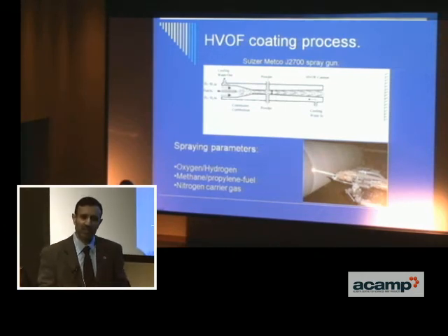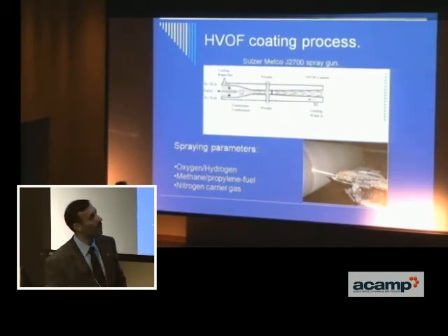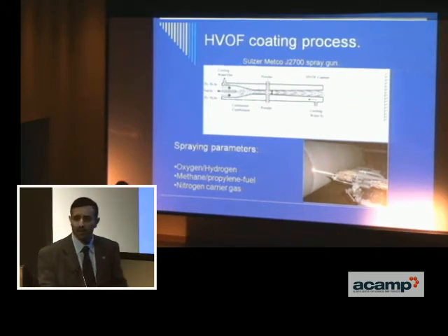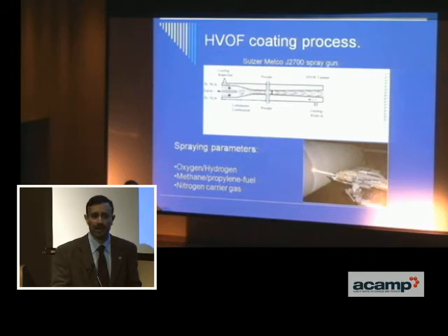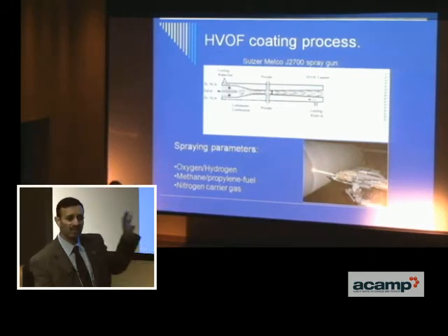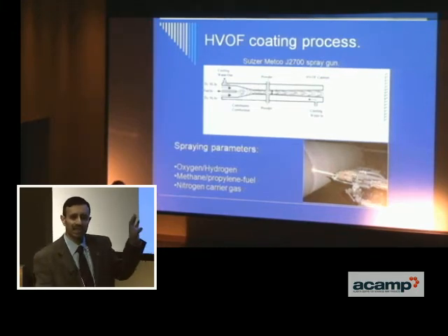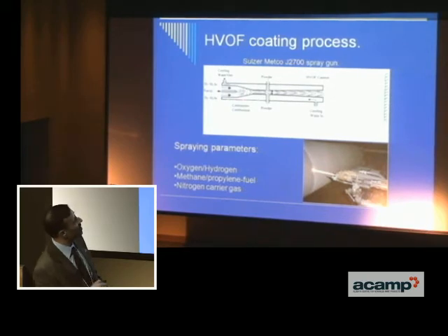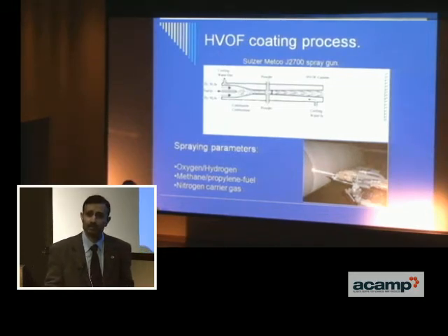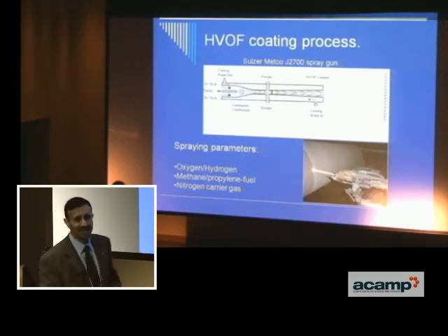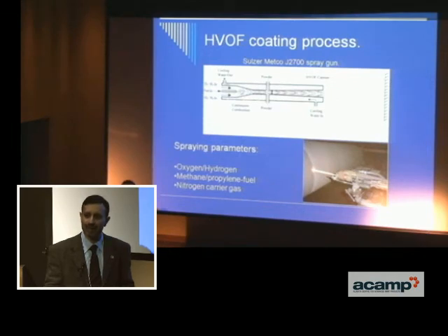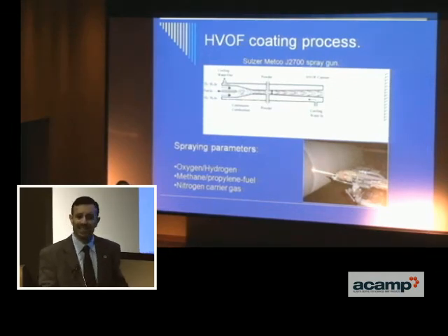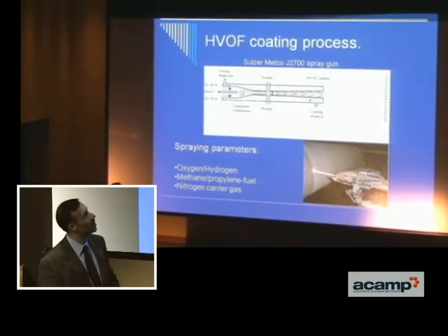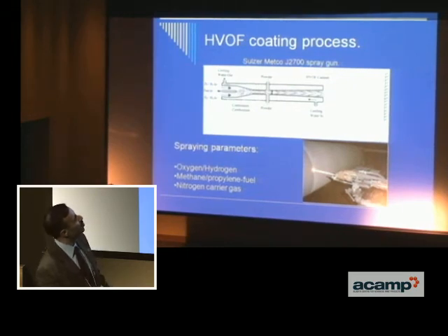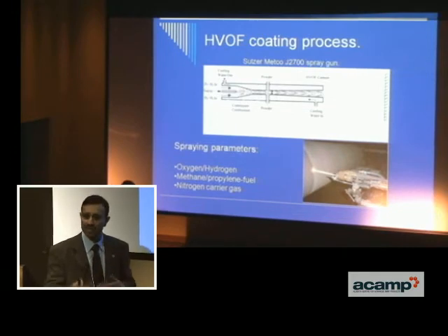So after a lot of extensive comparisons of different types of coating methods that we can use, we came down to using this particular process, and it's known as the high velocity oxyfuel spraying process. There's lots of different types of spraying processes, but for retaining nanostructure, this is one of the most effective. So we're producing a jet, there's an explosion that takes place in a chamber, and we shoot out the powder. Now there are two ways in which we can develop nanostructure. We can either develop it during the spraying process itself, or we can start off with a feedstock powder which has a nanostructure. So we've taken the easy route. We've taken the nanostructured powder and we feed it in through the gun over here. We feed it in, and the explosion and the fuel mixture allows us to deposit onto the substrate surface.